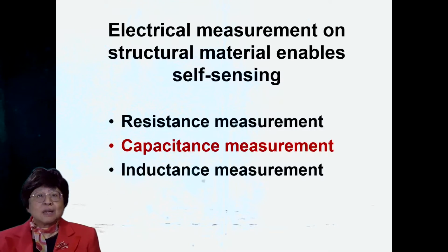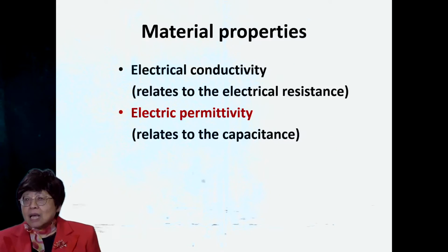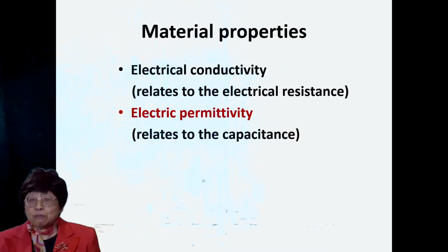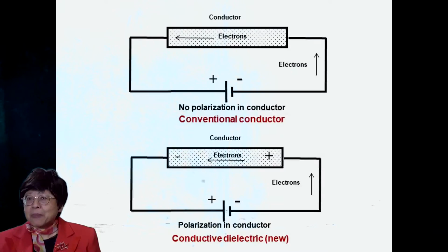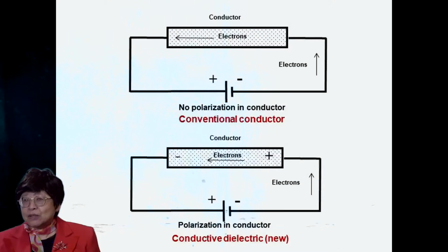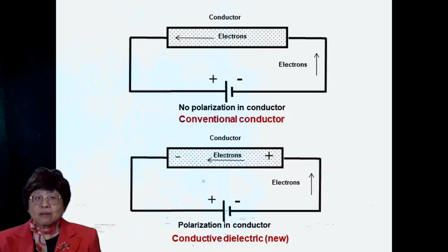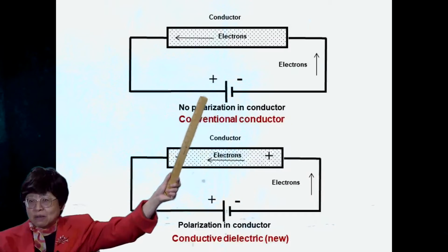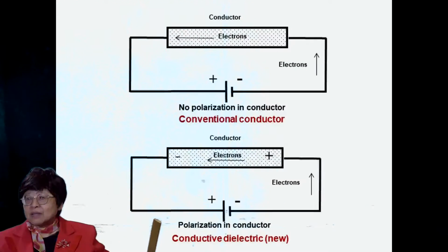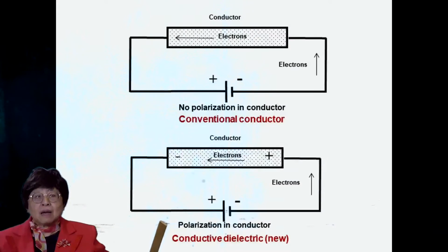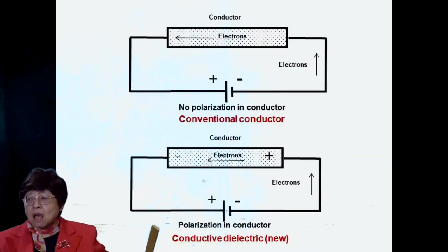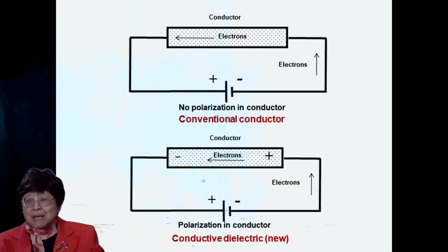So let me now turn to capacitance measurement. The conductivity or resistivity relates to the resistance, but the permittivity is a material property that relates to the capacitance. A conventional conductor does not polarize because there's no electron-atom interaction. The electrons just loop around. But here at the bottom is a case where there is a degree of interaction between a fraction of the electrons and the atoms. As a result, there is polarization. And this makes a conductor a polarizable or dielectric material.